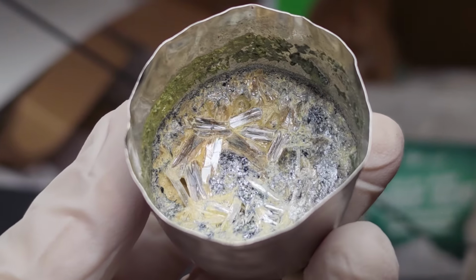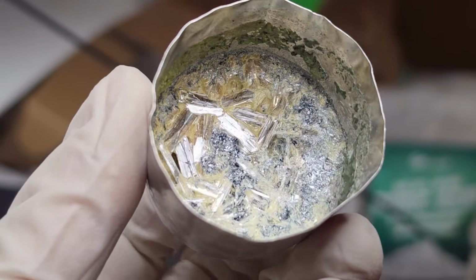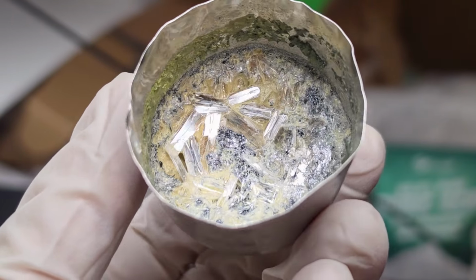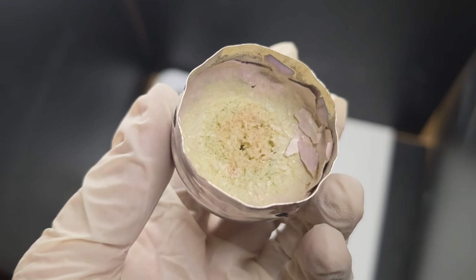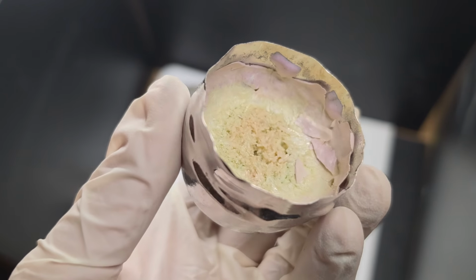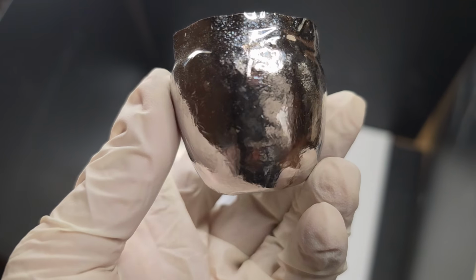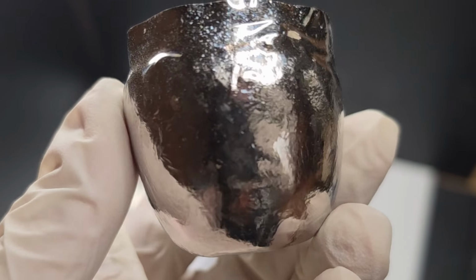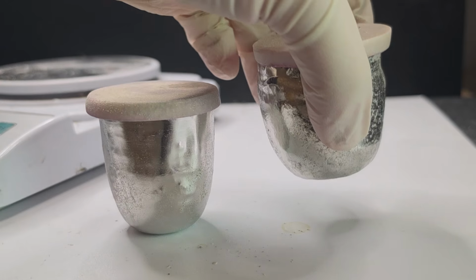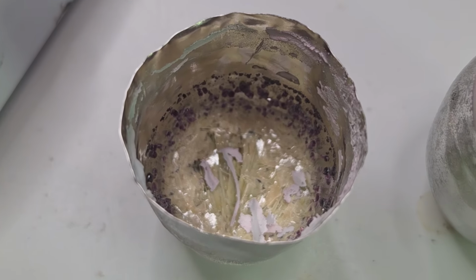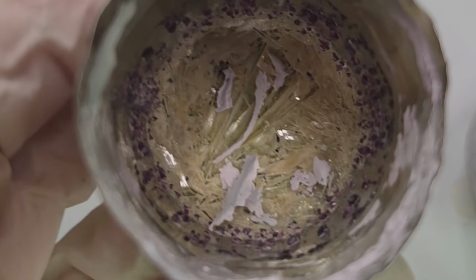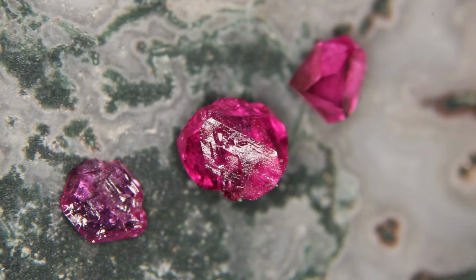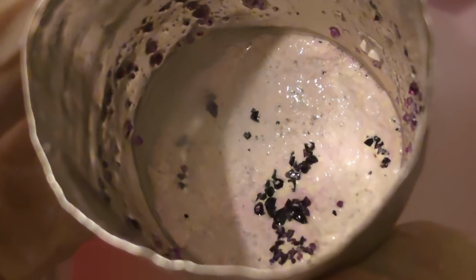The sodium tungstate mix formed some beautiful crystals of its own, but didn't make any rubies. And the lithium carbonate, well, it didn't grow any rubies, and it also turns out if you get the ratio wrong, it expands a ton as it cools. I'm really glad this didn't manage to burst because that would have ruined my day. But I tried again using much less of each reagent, and holy cow, the lithium mix came out great, with clear, beautiful rubies, setting a new record for size that the sodium tungstate mix immediately broke.